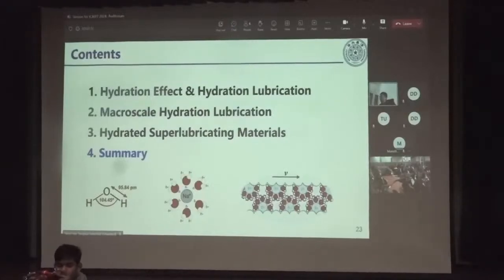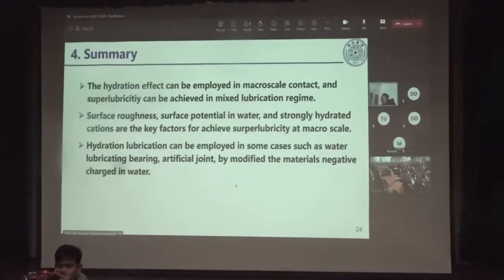Then let's go to the summary. First, the hydration effect can be employed in macroscale contact, and superlubricity can be achieved in the mixed lubrication regime. Second, the surface roughness, surface potential in water, and strongly hydrated cations are the key factors for achieving superlubricity at macroscale conditions. And third, the hydration lubrication can be employed in some cases, such as water lubricating bearings and artificial joints, by the negatively charged modified materials.